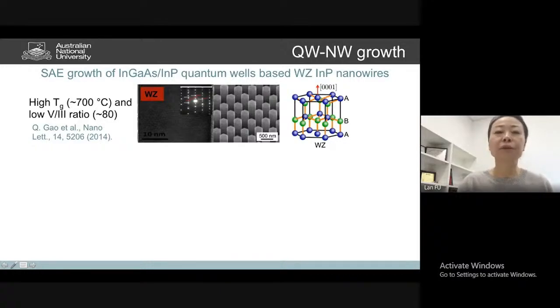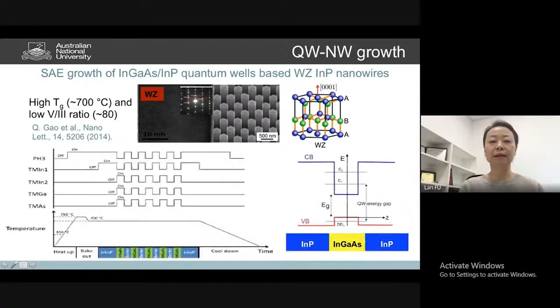So what we want to do is introduce a thin layer of indium gallium arsenide, which will be the quantum well material, because indium gallium arsenide has a smaller bandgap than indium phosphide. When we're doing epitaxy growth, we'll grow a short indium phosphide nanowire as a little base, and then we can switch in the precursors for indium gallium arsenide growth, for a very short time, a few seconds, because we want a thin layer. Remember, thin layer of quantum well, right?